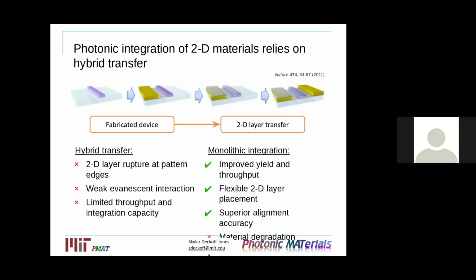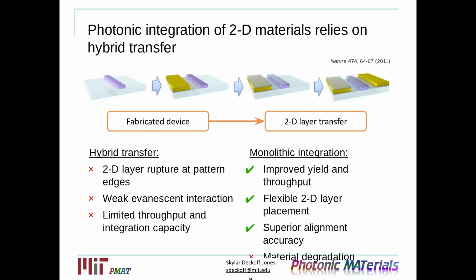So we propose a monolithic system where we can envision, rather than transferring the 2D material on top, we start with a substrate with an already existing 2D layer and then somehow fabricate the waveguide and contacts on top of the 2D material, which would allow higher throughput and other particular advantages, as well as alignment accuracy, which we'll see in the examples, which I'll talk about soon.